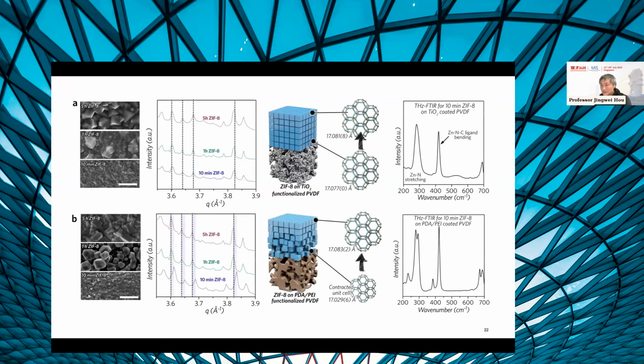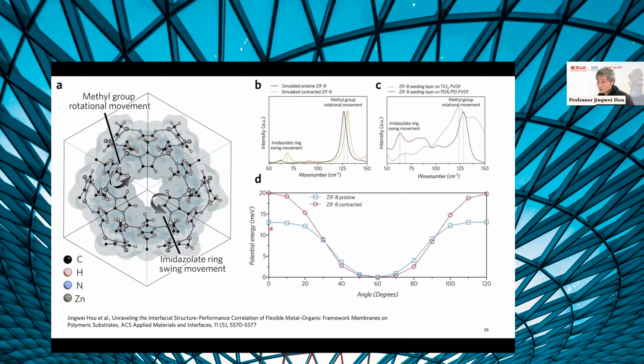Yeah, I think you are exactly right. So it's actually getting smaller. So the unit cell size is not that different. It's only about 0.3%, as I mentioned. But actually, I think two reasons. One thing is it's actually creating some defects for the crystal itself, making it mechanically less stable. The other thing is this is based on the DFT calculations. We put two unit cells into the DFT model. One is larger, the other one is smaller. So the smaller crystal model can reduce the rotation energy for the imidazole ligand. But I think that's another reason for the increased flexibility for the smaller crystal. I think probably the main reason is it's not at the lowest energy phase. That means we are actually disrupting the framework structure, making it less stable, or in other words, more flexible.